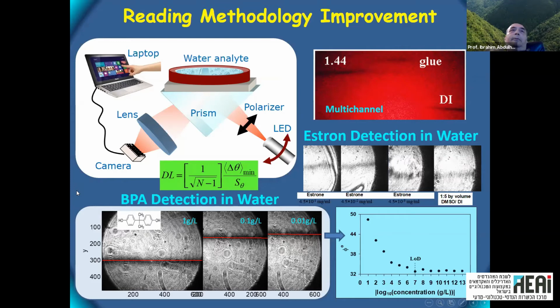So using this very simple setup, we managed to improve the system, let's say, a simple system, and it can give us 10 to the minus 6 quite easily. And we demonstrated sensing of many things with it. This was bisphenol A in water, estrone in water, with detection limit of something like nanograms per milliliter. The latest one was a biomarker for stroke detection in water and in plasma.